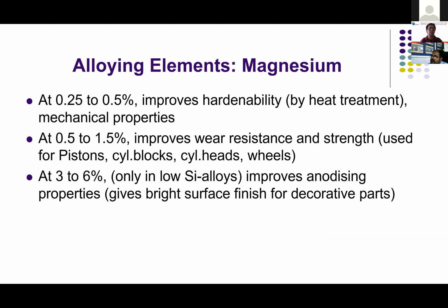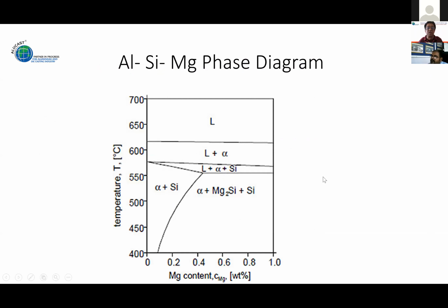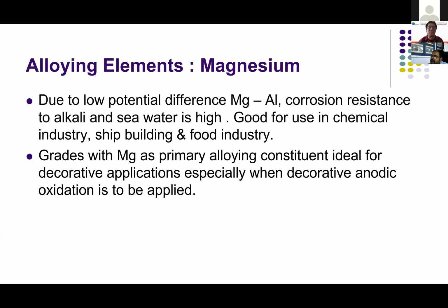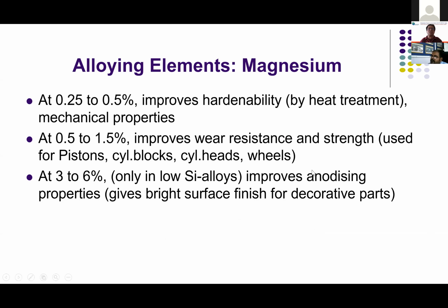Now coming to magnesium, normally it is added between 0.25 to 0.5%, and improves the hardenability by heat treatment. Here also the same thing happens. I'll show you the aluminum, silicon, magnesium phase diagram. I'll come back to it slightly later again. Magnesium also has the same property as copper. When heated above 400 degrees centigrade, the magnesium in the Mg2Si phase dissolves inside the aluminum structure, and then it reprecipitates during controlled cooling and other processes in heat treatment.